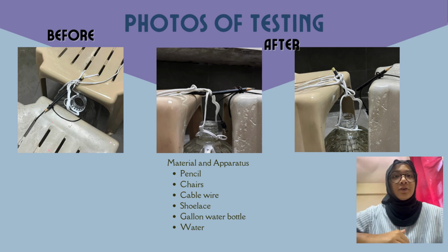The experiment concluded when the volume reached 6.38 liters, at which point the pencil underwent a complete fracture. This result indicates that the material reached its highest bending moment at this load. The sudden nature of the break signifies the transition from elastic deformation to a brittle failure. This confirms that the material had exceeded its ultimate strength.